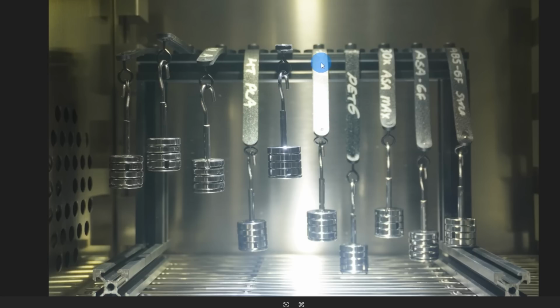Now this is the High Temp PLA glass fiber that's unannealed on this one right here. This is the annealed part. So it's dripped a little bit, but considering that's 50 grams hanging 100 millimeters out on that tiny little part, that's pretty damn good. This is the High Temp PLA, not the glass fiber, again unannealed, and you can see how much it's pulled down. But I want you to notice that neither the High Temp PLA nor the High Temp PLA glass fiber that are unannealed have failed near as much as the ABS and the ASAs or the PETG. Now the annealed stuff, it's doing really, really good.